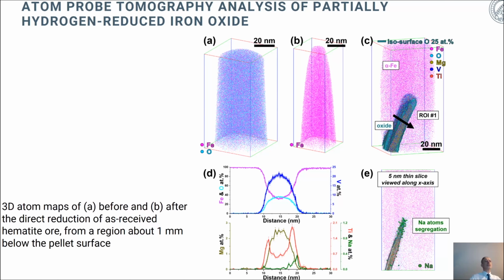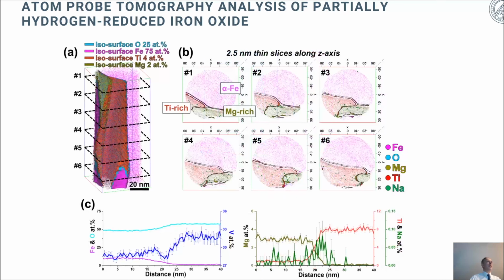Another point is that you also form other types of oxides. Here, for instance, we find more complex oxides based on sodium or also on magnesium. And these, as you know, have very high enthalpies with the oxygen, which makes them harder to reduce by hydrogen, so that some of these oxides prevail as the reduction goes ahead. And here's another picture that shows similar features with not only magnesium-rich oxides, but also titanium-rich oxides, which remain in the pellets during the reduction and can make the process more sluggish.